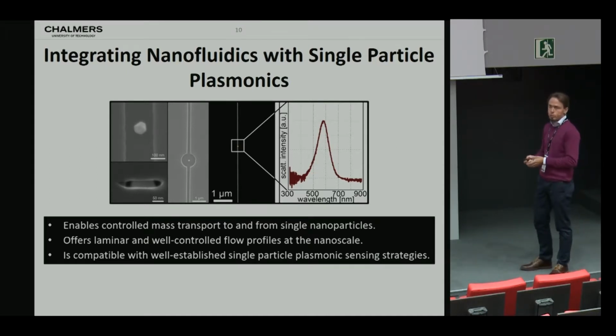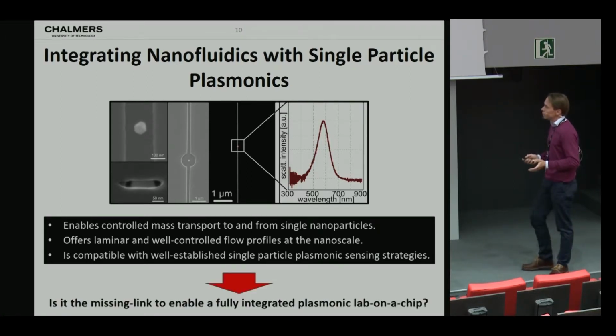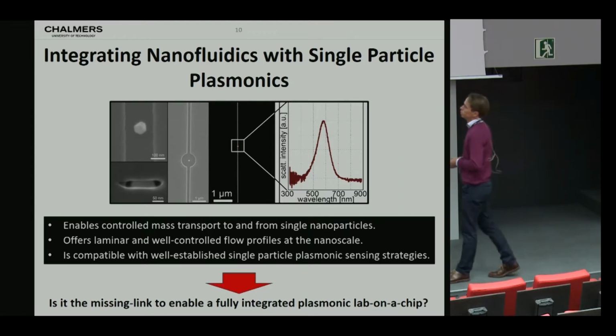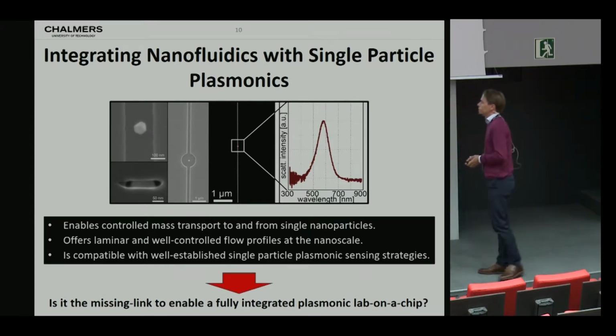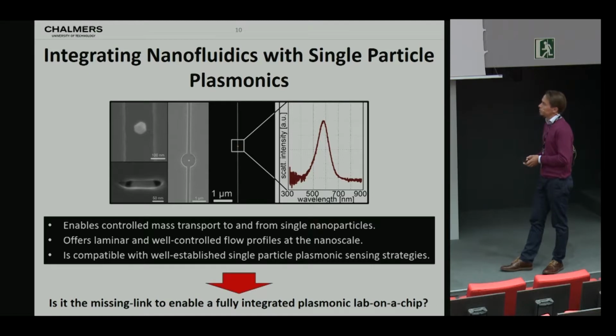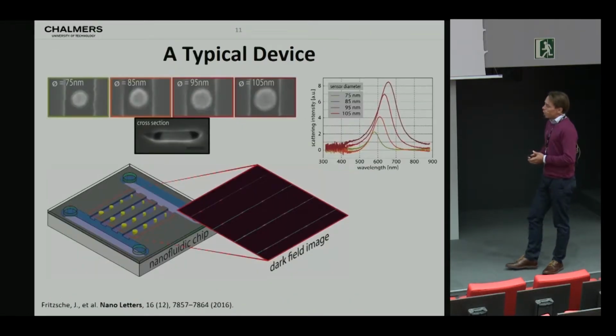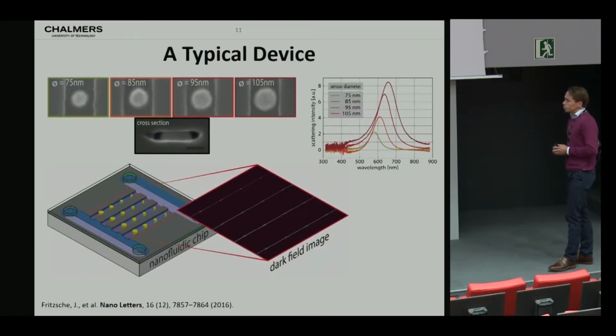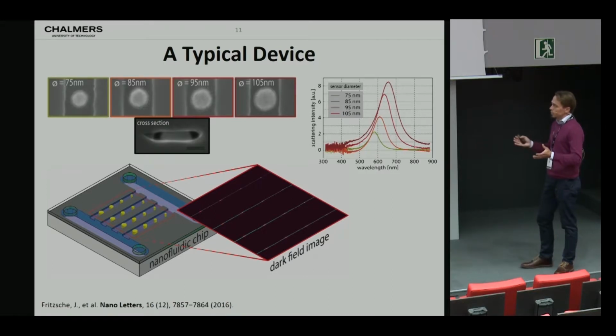So you can nicely resolve the scattering spectrum of a single gold nanoparticle located in this nanofluidic channel, which here is highlighted, and it's not the background scattering from the walls. This you can suppress. So the question is, is this one of the missing links to ultimately enable fully integrated plasmonic lab-on-a-chip devices? So let's now get a bit more specific and look at how such a typical device that we make could look like.